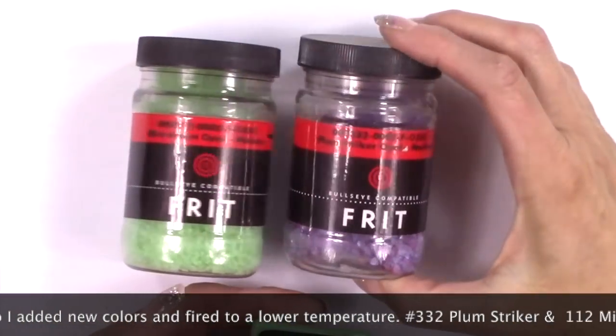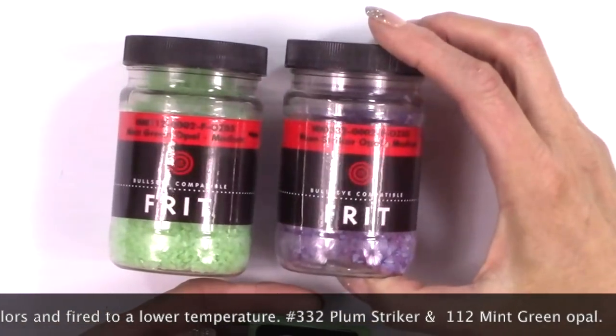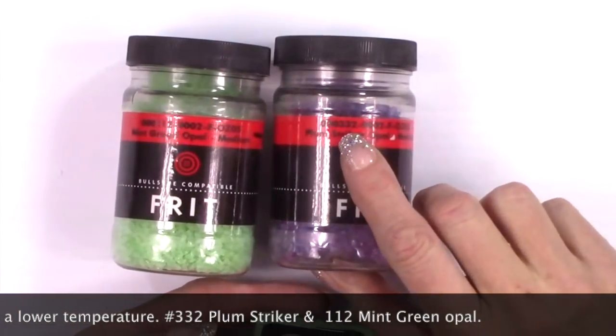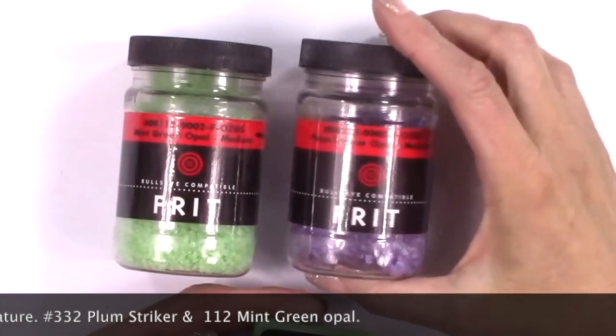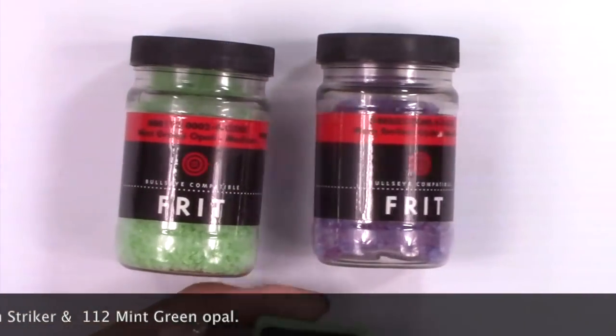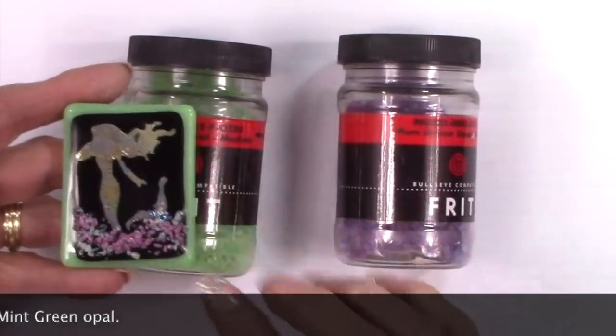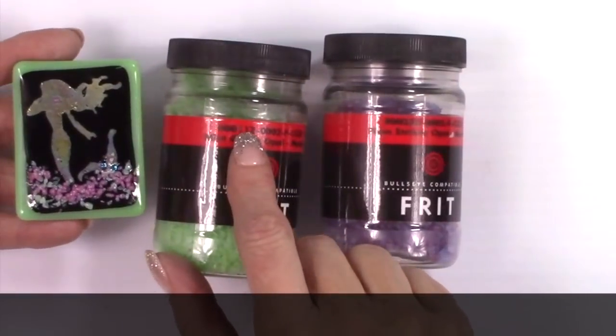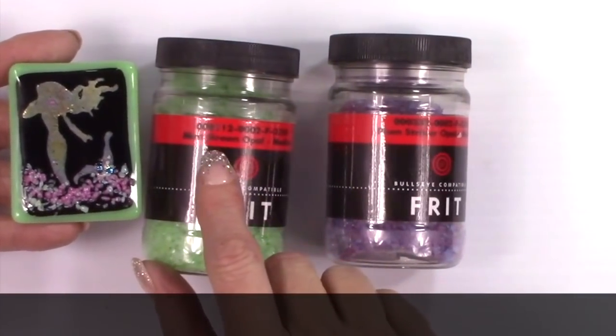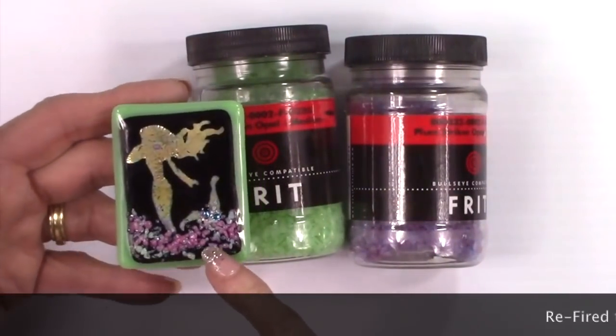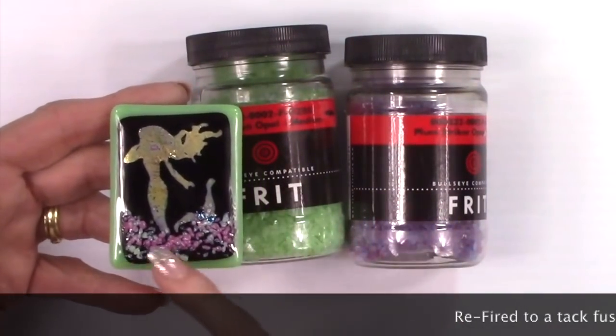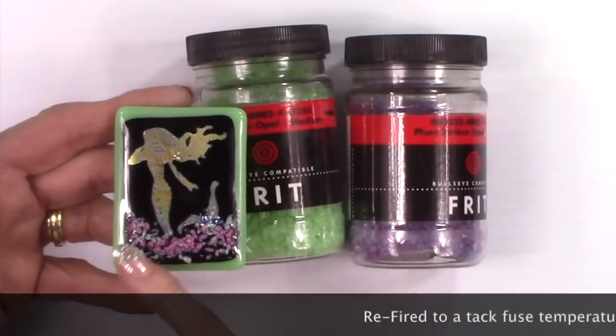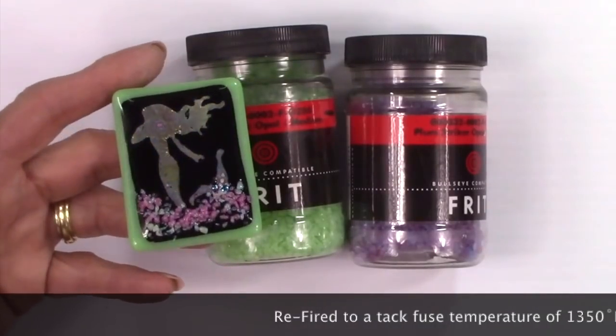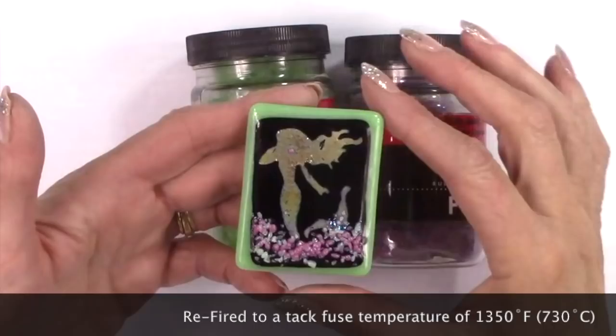This time I used Plum Striker, which is number 332, and it can be very expensive, but I used such a tiny amount that it was so little that it doesn't cost very much at all. And 112, the Mint Green Opal, and I mixed that and put this at the base, and then I fired it to a tack fuse, so only to 1350, and that looks much better.